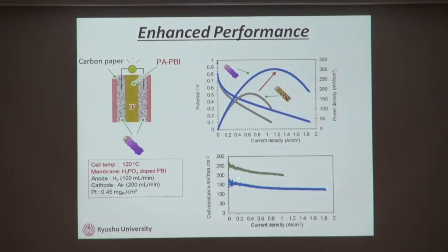And when we use a film with low resistance like this, we found that our fuel cell performance increased from here to here. Last time maybe 120 milliwatt per square centimeter, but when we decrease resistance, the fuel cell performance reached almost double. So this result indicates that we can improve the performance more. And this is rather high, but we can improve more in a year or 2 years.